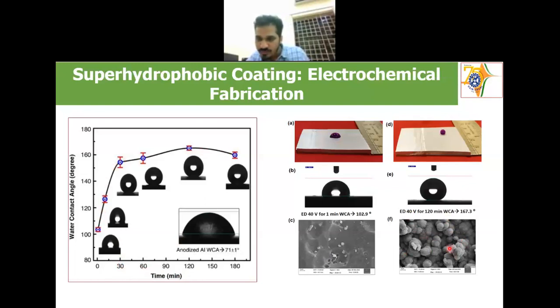This is how the surface looks through the FE-SEM image, and how a water droplet is sitting on the coated surface. We found that as it increases up to 120, we are able to get the superhydrophobic regime and complete coverage of the surface. But when we increased to 180 minutes, we found a slight decrease in the contact angle.